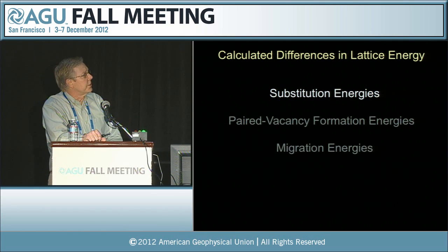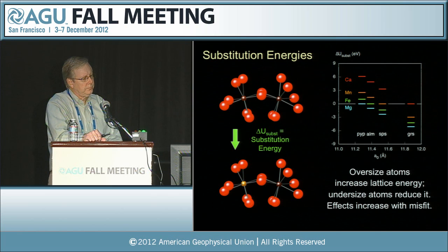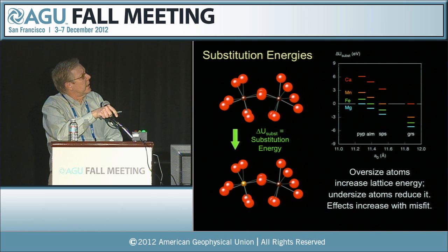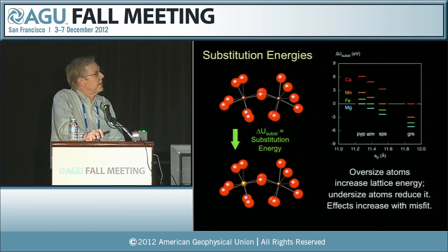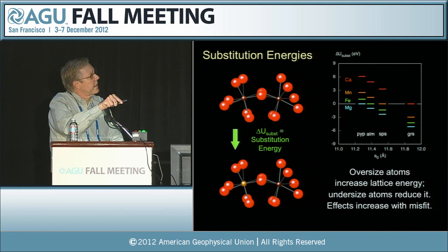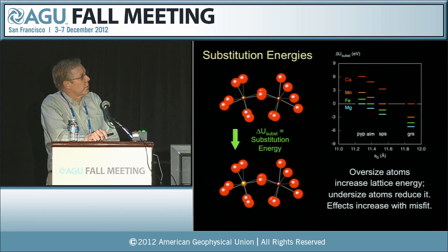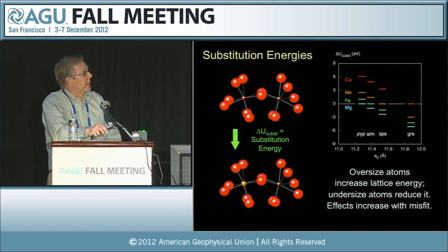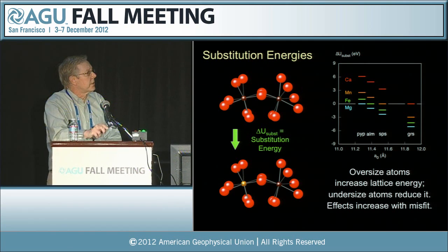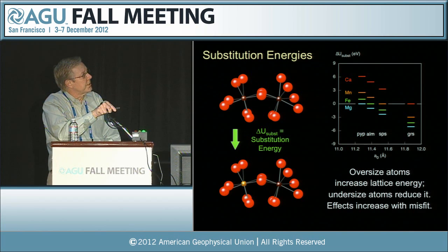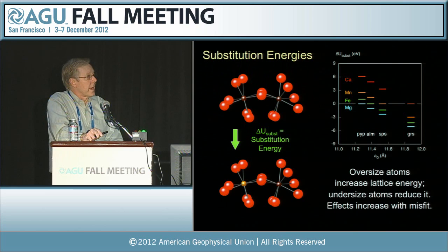Let's start with the substitution energies. The substitution energies are plotted here on the vertical axis, and they are shown for each of the 4 divalent cations in each of the corresponding end members. And they're plotted on the horizontal axis as a function of the unit cell dimension of those end members. It's very clear here that oversized atoms increase the lattice energy. That's not unexpected, but maybe surprisingly, these undersized atoms actually reduce the lattice energy.